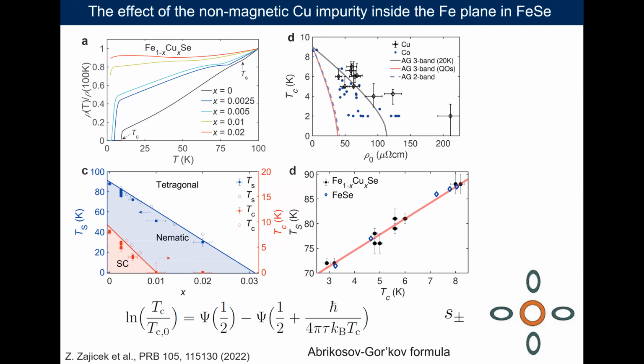So this is equivalent to what has been done in cuprates in the case of a magnetic impurity. When we have a sign-changing order parameter, then we need a non-magnetic impurity to follow a similar formula. So Tc follows this. That means we are likely dealing with an S plus minus superconductor in iron selenium. And also the nematic phase and superconducting phase seem to be affected in a similar way by impurities.